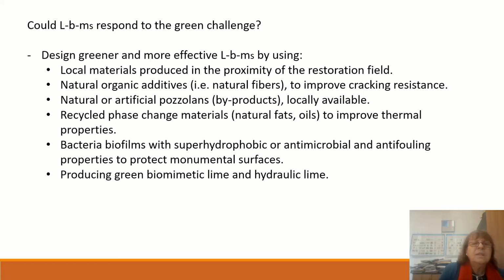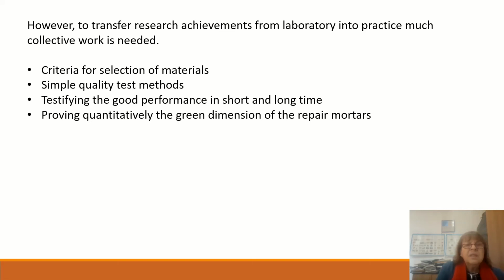Also local, natural or artificial pozzolanic materials, natural organic additives to improve cracking resistance, recycled phase change materials in order to improve thermal properties, bacterial biofilms with superhydrophobic, antimicrobial and anti-fouling properties to protect monumental surfaces. And also we can produce green biomimetic lime and hydraulic lime. However, to transfer these achievements from the laboratory into practice, much collective work is needed. We need criteria for selecting materials, simpler quality test methods testifying the good performance in the short and long term, and proving quantitatively the green dimension of the mortars.